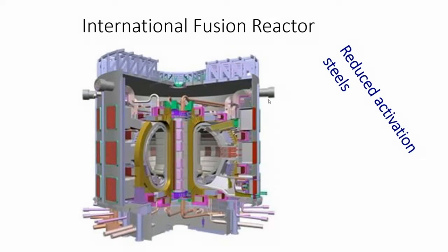So typically in a normal reactor, a fission reactor, you would have 30 displacements of every atom in your material over the service life. With a fusion reactor, we expect 200 displacements per atom in your material. Now, imagine the pain the material is feeling, you know, when the neutrons knock every atom out of position 200 times. So that changes the structure of the metal in two ways.